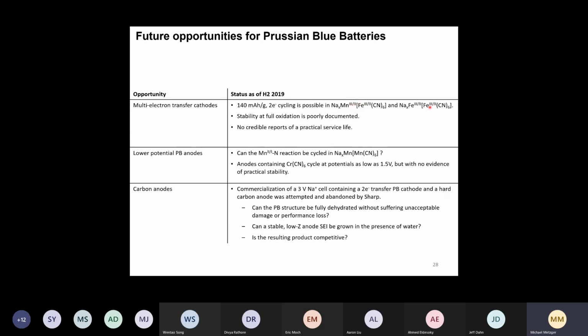Also in the iron hexacyanoferrate material, you can do this, but it is not well documented in literature what happens at this full oxidation of the material, whether it's still stable or not. And, you know, there are no credible reports of practical service life. For sure, Natron is working on this. So that's a very interesting avenue to increase the specific capacity of these materials.